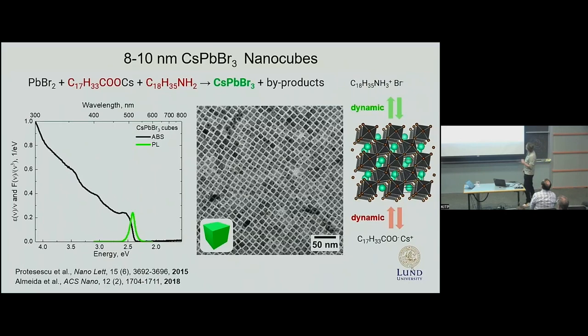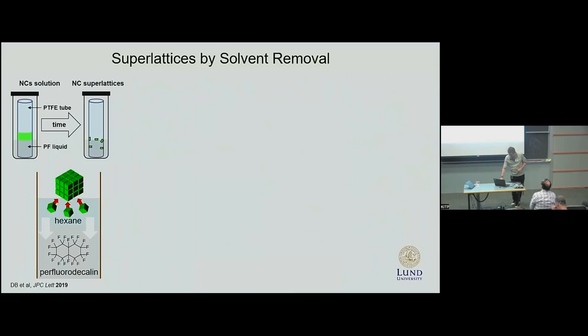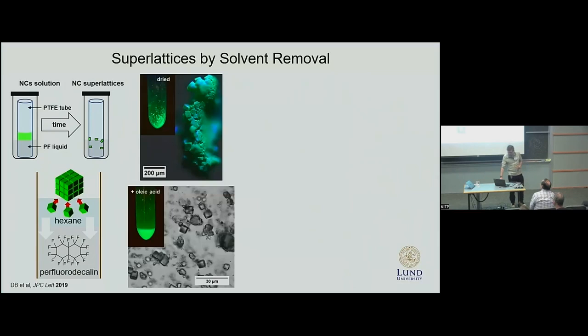They have quite an interesting and dynamic surface chemistry. First we started making self-assembly by solvent removal. In essence, we dispersed perovskite nanocubes in hexane, a good solvent, and deposited it on the surface of perfluorodecaline, a solvent which is miscible with hexane but a bad solvent for nanocrystals. Hexane diffused, producing these cuboidal objects.